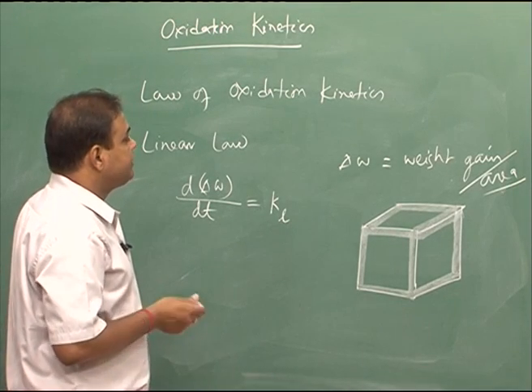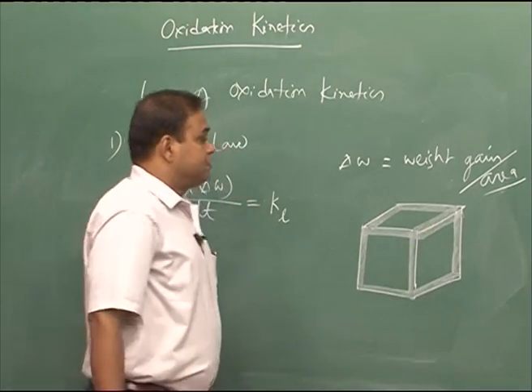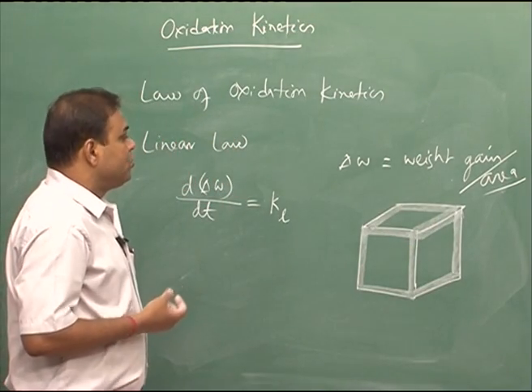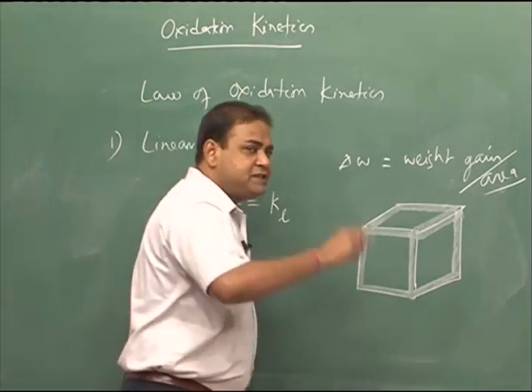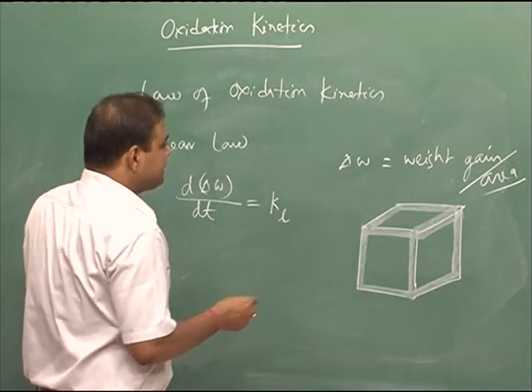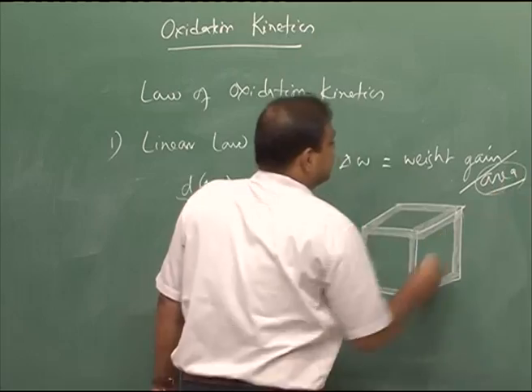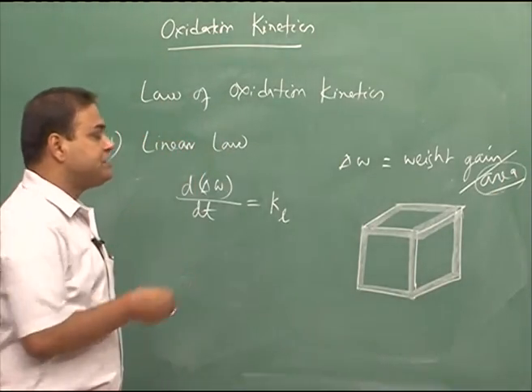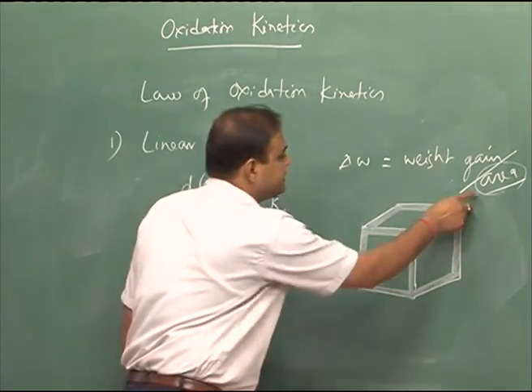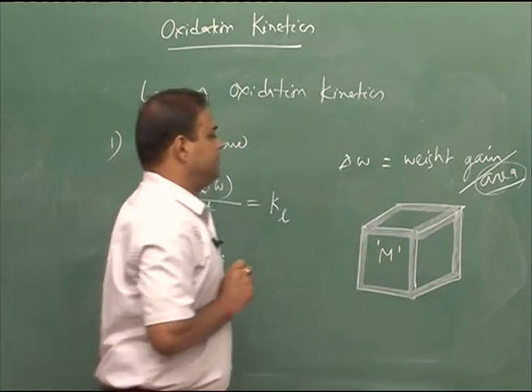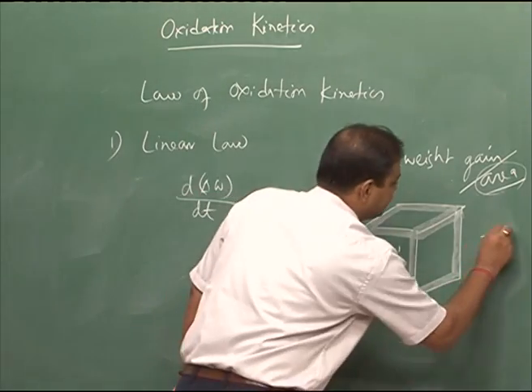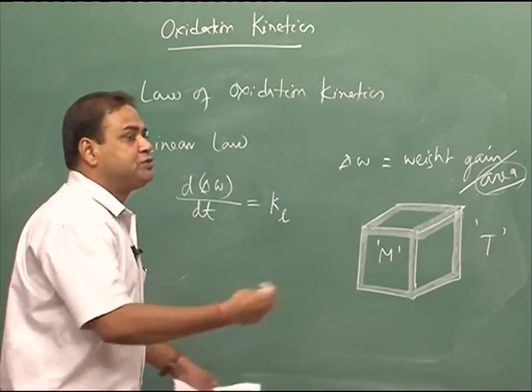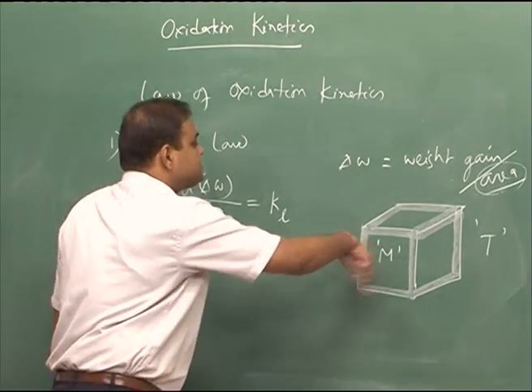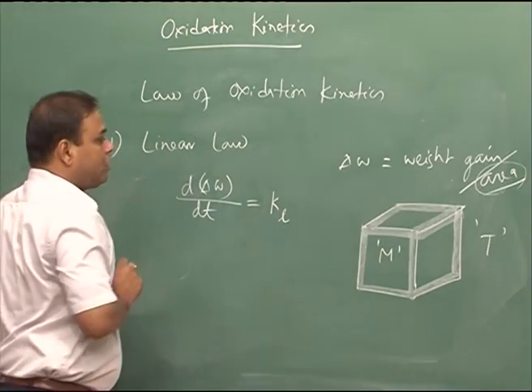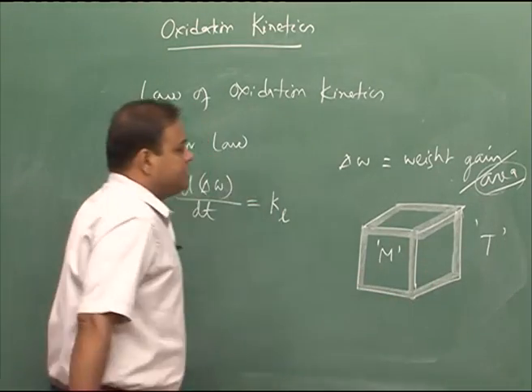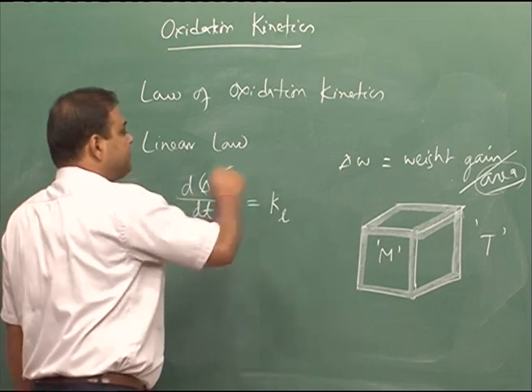As well as whenever we are considering the thickness of the oxide that is gradually increasing, we are assuming that the oxide layer is sticking to the surface. So, that means if we increase the area, overall weight would increase, but if we divide it by area for a particular metal at a particular temperature, that would remain the same, because if that oxidation process is following the linear law at a particular temperature T, it should have a constant relation.